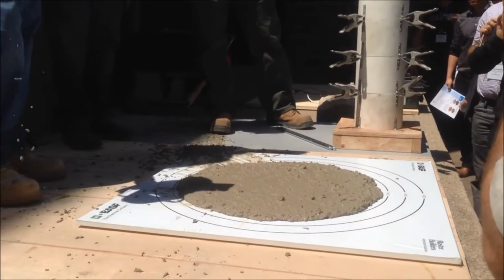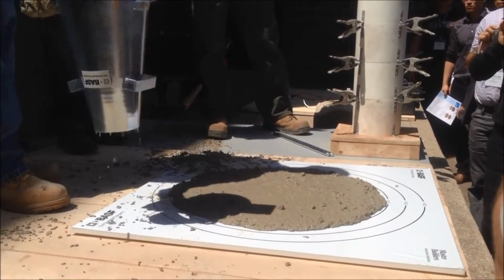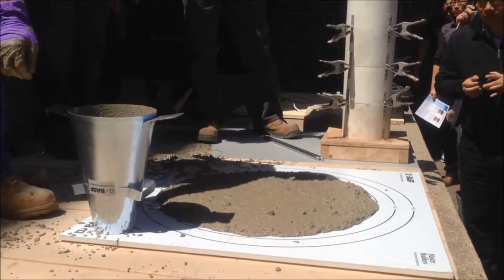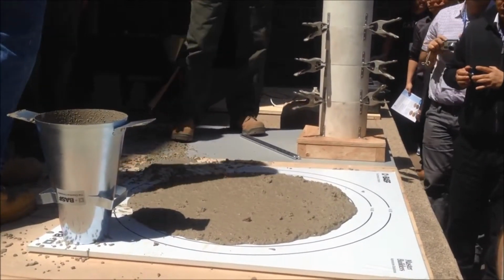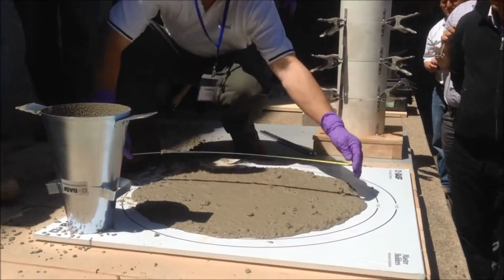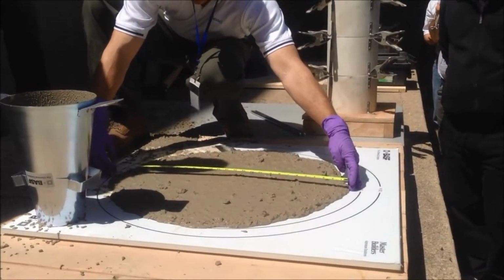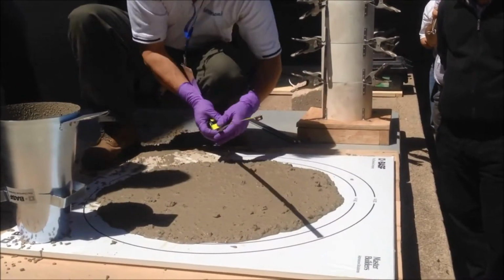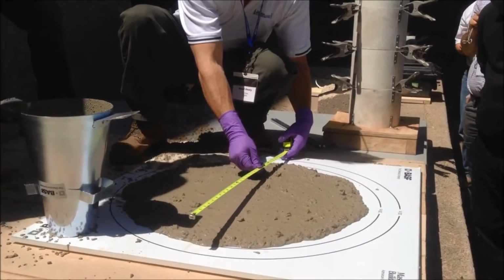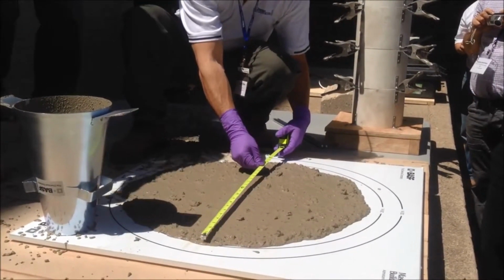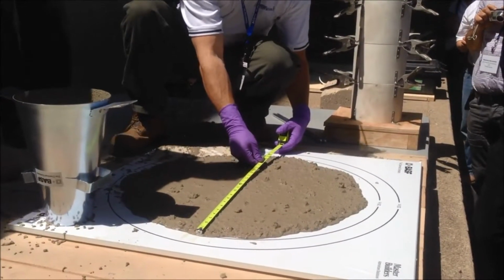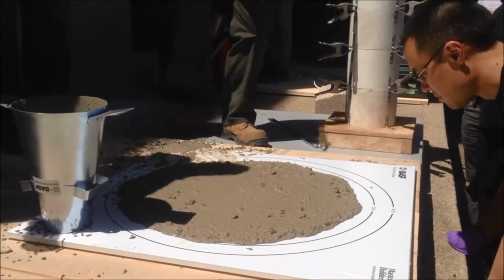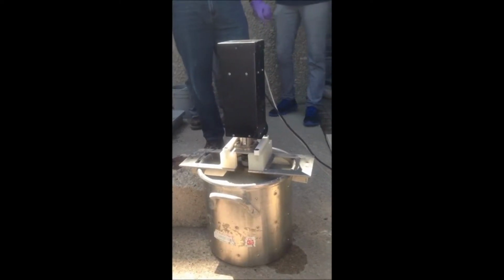The flowability of self-compacting concrete is usually measured in terms of flow or spread using the modified version of the slump test. That slump flow typically ranges from about 450 to 800 millimeters depending on the requirements for the project. The viscosity of self-compacting concrete too is an important characteristic of its plastic state and can be controlled when designing the mix to suit the type of application being constructed.